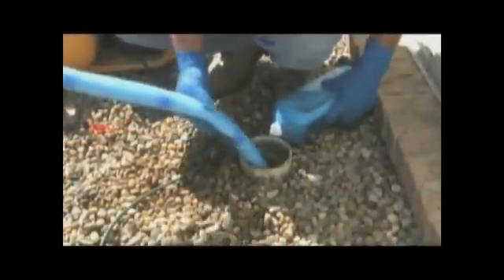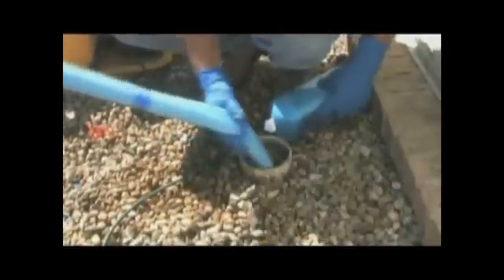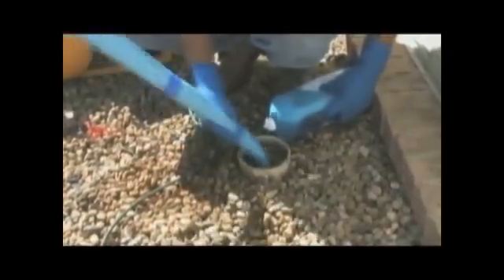We videoed the inside of the line before and after. And as you can see, it has sealed the holes and smoothed out these areas that would have caught paper or caused stop-ups. With this method, we can repair most types of pipe without digging. We can actually take the liner through a commode flange or clean out in most cases.